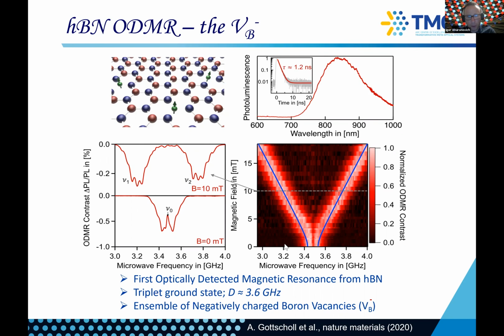And partially it may be because the emission is already oriented in a specific way, and we work with a very high NA objective. So we probably already collect the light in the same kind of collection angles from the surface and from the pillar. So it's hard to say if it's more directional, but it is definitely brighter. It's about 2 to 3 times brighter than if you would have collected from just a normal plain substrate. So there is definitely an enhancement in this regard, but directionality-wise, we don't really know. Okay, thank you.